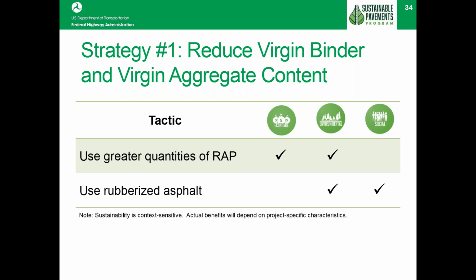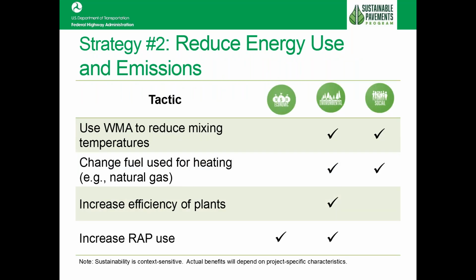A good example of this was the Illinois tollway. The tollway used 40 to 60% binder replacement in asphalt pavements using fine fractionated reclaimed asphalt pavement. Fractionated RAP is where they split the stockpile RAP between coarse and fine fraction. Another strategy is to try and reduce the amount of energy used both at the plant and during construction, and reducing the emissions as well.